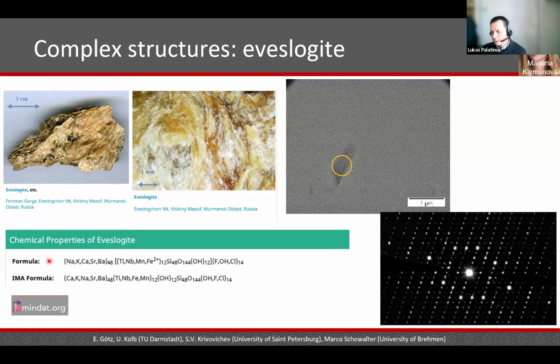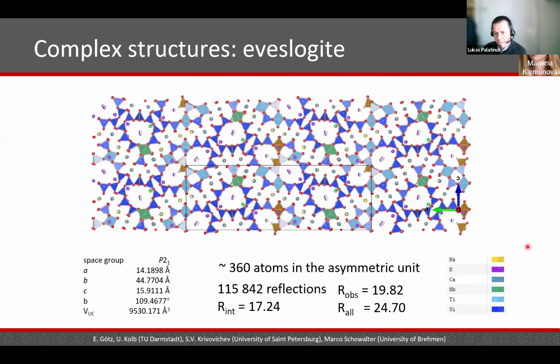But when looking at the diffraction, this is what we saw. It diffracts beautifully. It shows that despite the complexity, the structure is very, very well ordered. And indeed, it was possible to solve the structure just with standard approaches. And this is the structure. It turns out to be one of the 10 most complex mineral structures known to date, with 360 independent atoms, so over 700 atoms in the unit cell.